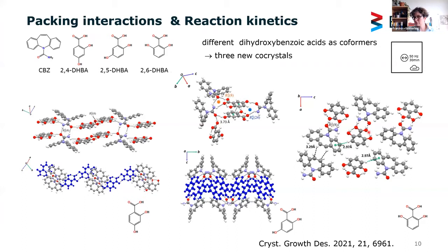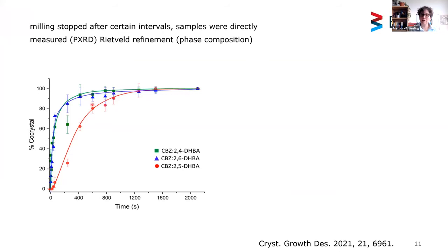So we were now interested to learn a bit more about the kinetic profile of these reactions, and therefore we performed experiments for a certain amount of time, stopped the experiment, and then did Rietveld refinements to check for the phase composition. And these data are shown here, and you can see that the co-crystal between carbamazepine and the 2-4 compound and the carbamazepine and the 2-6 compound show a similar profile, whereas in the other case, the 2-5 compound, there is a different profile.